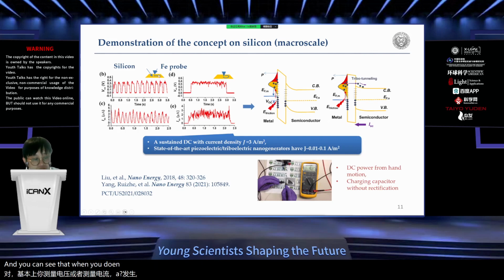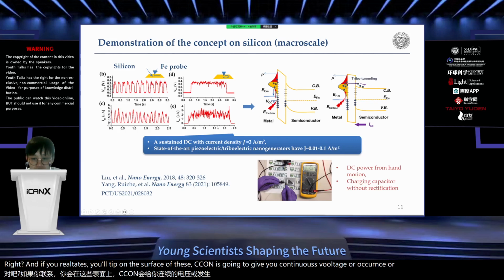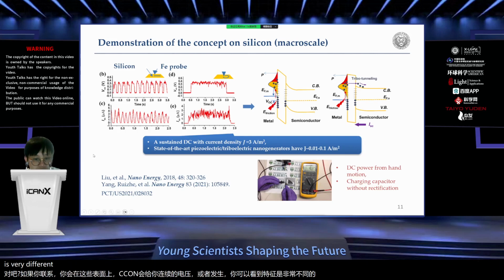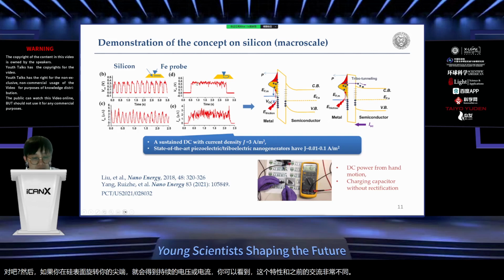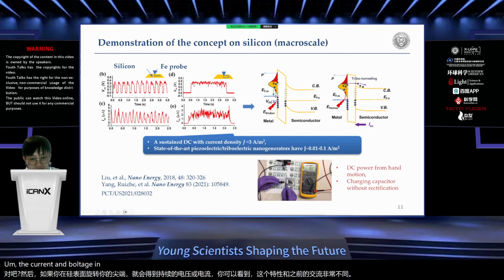And basically you measure the voltage or the short circuit currents. And then you can see that when you do linear motion back and forth, it's going to give you voltage and current at the same time, right? And then if you rotate your tip on the surface of this silicon, it's going to give you continuous voltage or current outputs. And you can see that the feature is very different from the previous AC one, since the currents and voltage output are in phase, right?